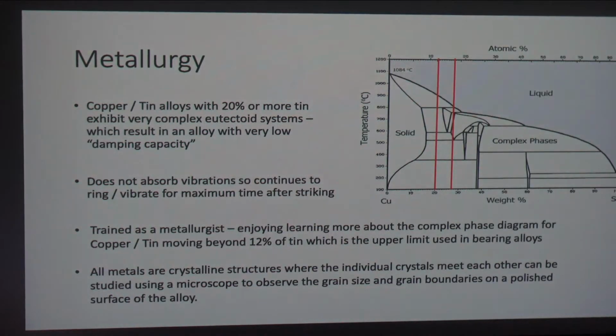So, metallurgy, for a brief exploration of that. You can see the phase diagram there on the right hand side, and between those two red lines is the composition that most bells are made. It's really just two different elemental metals, but the alloys are incredibly complex. There are a lot of eutectoids created, and they all mix together, so you've got a very, very long freezing range, from the point that it first goes from liquid to solid to the point when it's finally frozen off. It starts up there somewhere about 950 degrees and doesn't finish being solid until you're right down beneath 300 degrees.